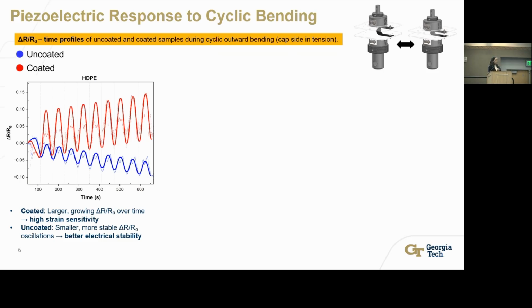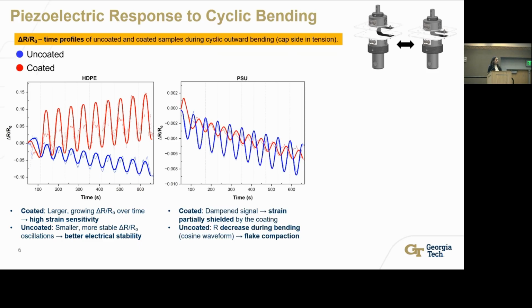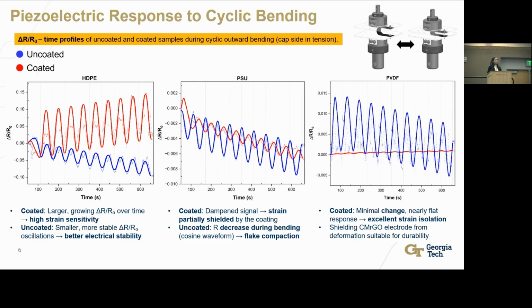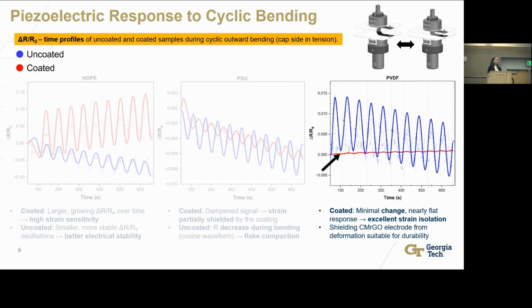It's actually showing a larger strain when compared to its uncoated counterpart given in blue. And this shows high strain sensitivity, but if you look at the PSU sample, we actually get a dampened signal. So we can see that the strain is partially being shielded by our cap. And if we move on to the last material group, you're going to see almost a flat line with the red coating. And this is once again showing the PVDF case standing out, showing excellent strain isolation.